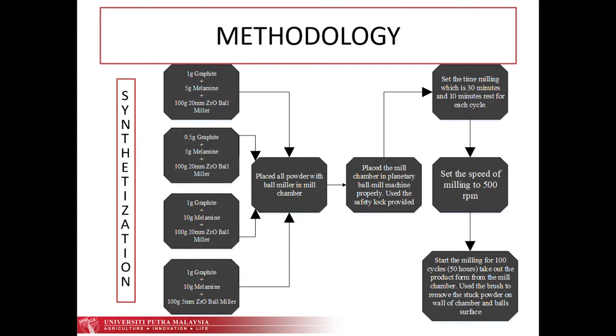For synthesization of the nitrogen doped graphene, 4 samples were made. Sample 1 is 1 gram graphite plus 5 gram melamine plus 100 gram of zirconium ball miler with 20 millimeter diameter. Sample 2 is 0.5 gram graphite plus 5 gram melamine plus 100 gram of 20 millimeter zirconium oxide ball miler. Sample 3 is 1 gram graphite plus 10 gram melamine plus 100 gram of 20 millimeter zirconium oxide ball miler. And the last, sample 4, is 1 gram graphite plus 10 gram melamine plus 100 gram of 5 millimeter zirconium oxide ball miler.